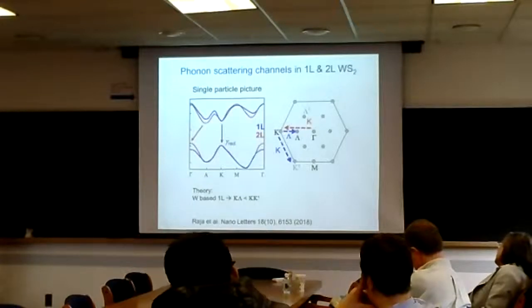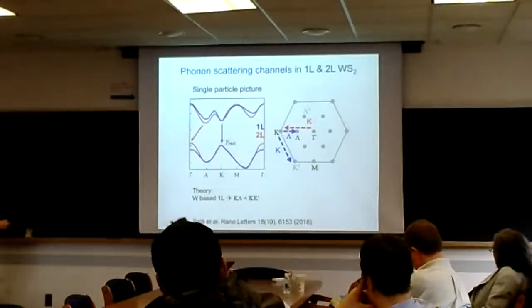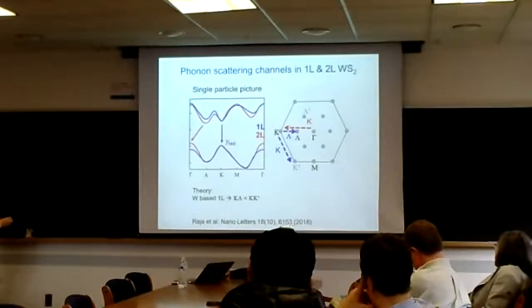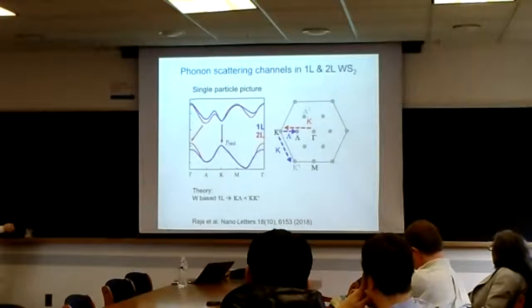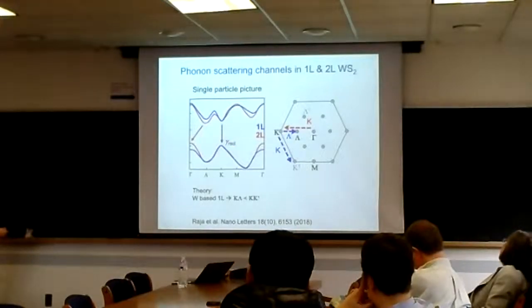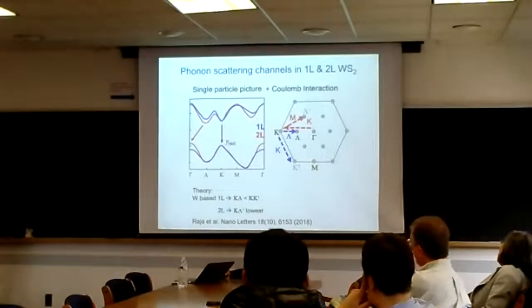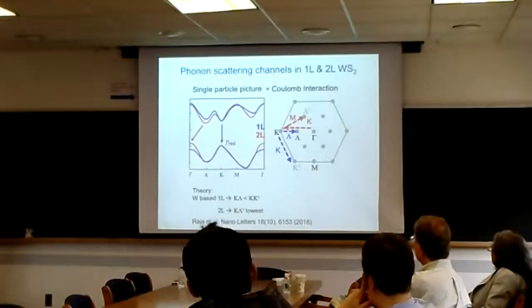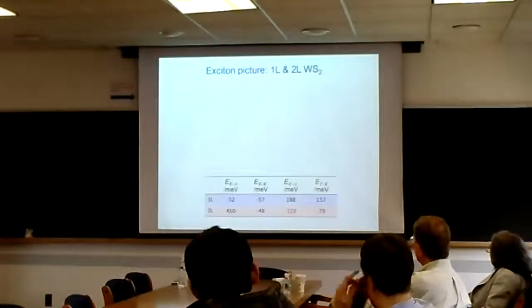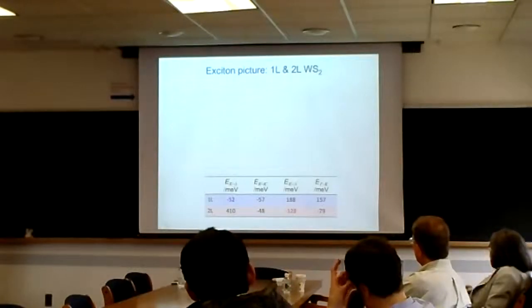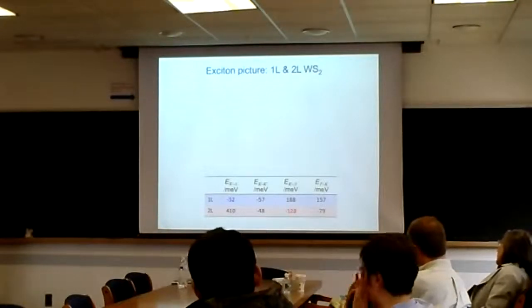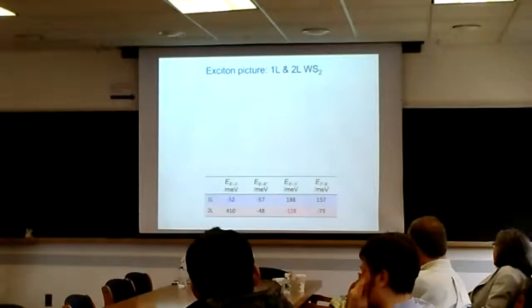Now, in the case of the bilayer, just to repeat the point that I made earlier, it becomes an indirect gap material, and there's this new transition that's the lowest-energy transition. You would think that moving from K to gamma would be the dominant interaction. But what we found is that it's a completely different phonon mode that contributes to this. So the take-home message is that you can have new processes that arise because of the screening, which were not present previously, and that can tune your phonon interactions with your exciton.